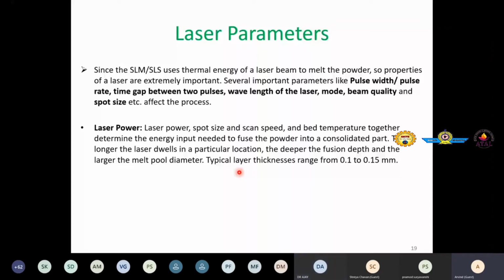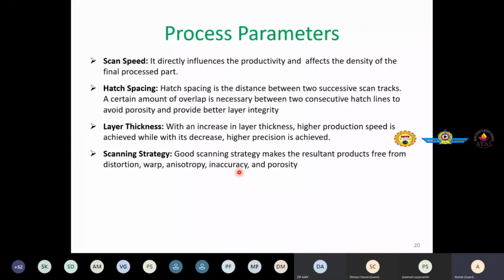Also, the microstructure refinement would be achieved, which will lead to enhanced mechanical properties. After laser parameters comes process parameters. So here the process parameters, you can very well guess what could be the main process parameters, like say scan speed, hatch spacing, layer thickness, scanning strategy.